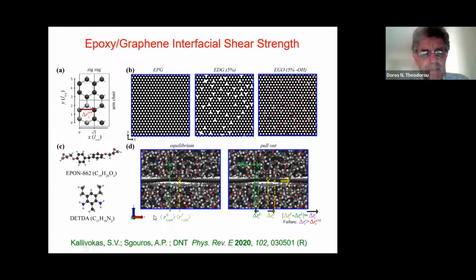And within the polymer, we enclosed a graphene sheet. What you see here is the profile of a graphene sheet. This graphene could be either pristine graphene, pure graphene, or it could be defective. We could pluck out some carbon atoms out of it, or we could plant some OH groups on the graphene to form what is called graphene oxide, because we wanted to look at the mechanical properties as a function of the chemical constitution of this nanofiller.